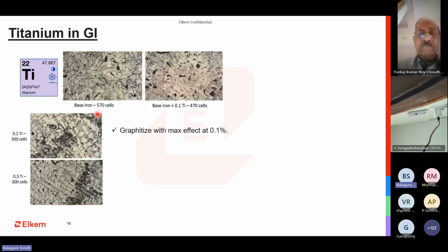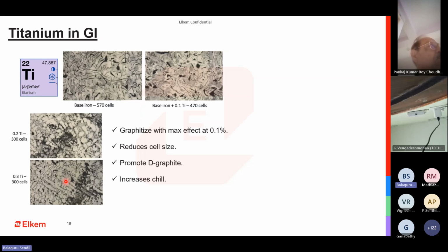That is very important, because so far we have been happy to use whatever material we have. We are getting titanium from there. Our base titanium was low, but now the base titanium is going to keep increasing. Then we need to have much better focus and control on all those other variables to control titanium. So as I told, 0.2, 0.3, it makes it further worse. You can see for yourself how the microstructure goes bad. It reduces the cell size, promotes D-graphite, increases chill. So for gray iron, titanium is going to be a very big problem unless you are able to control it, or unless you are able to neutralize the effect of titanium with proper preconditioning.